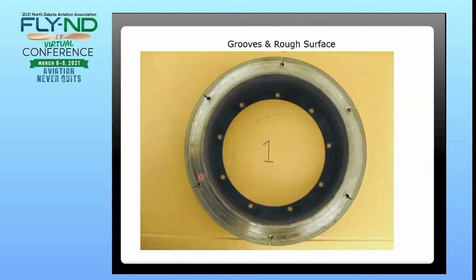Here's that 414, also the brake disc, what it looked like. So the darker part here, from the 6:30 position to about the 9 o'clock position, that dark spot, that broke in there, and then the rest of the disc was not broken in properly. So that just tells me that he changed the brake disc out and did not do a braking procedure. And then this was from the first application of the brake disc, and it just got worse and worse and worse as time progressed.